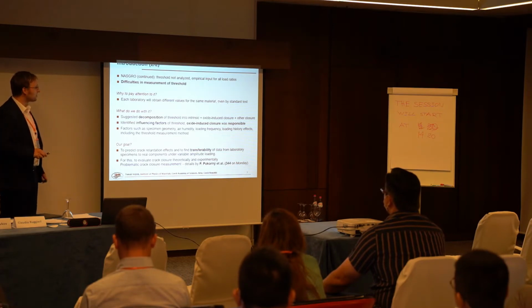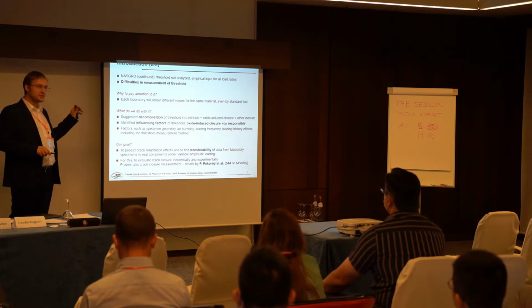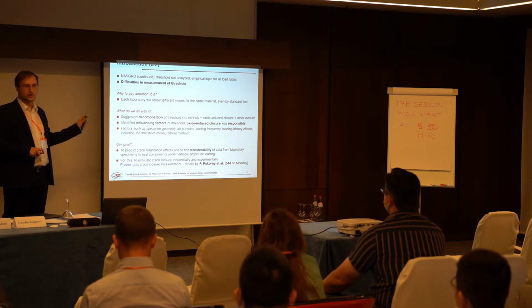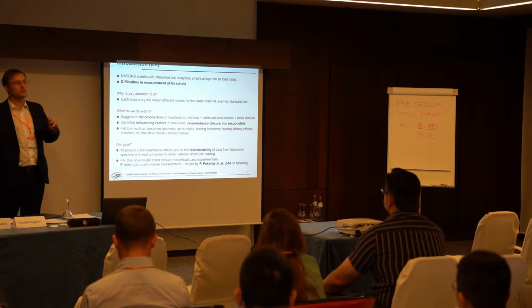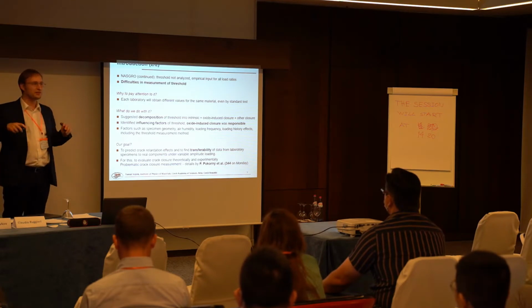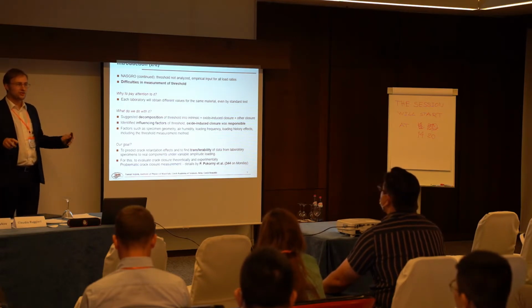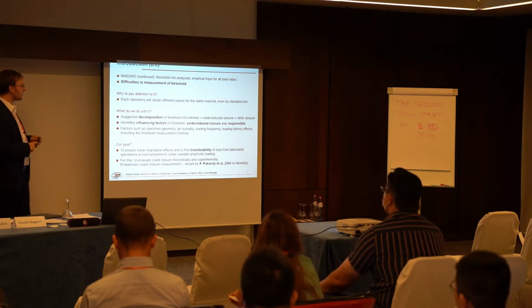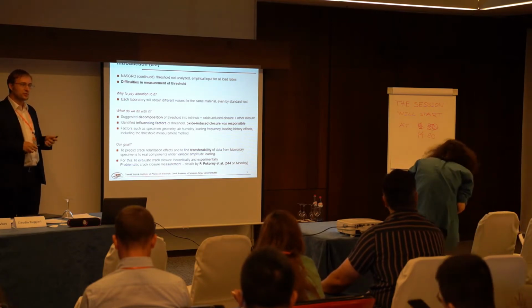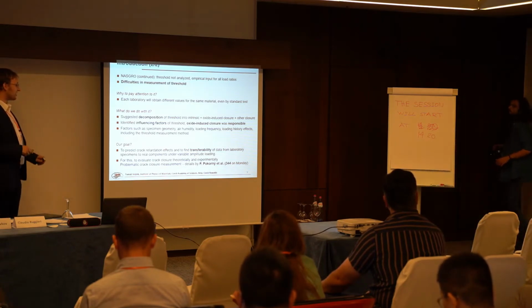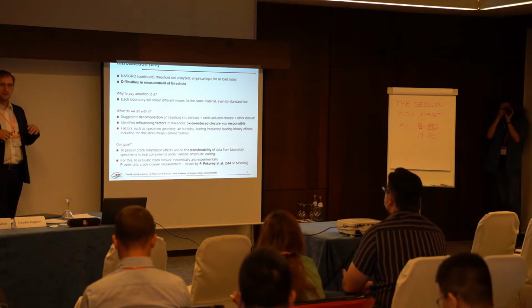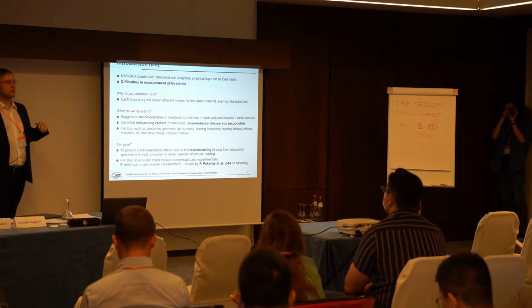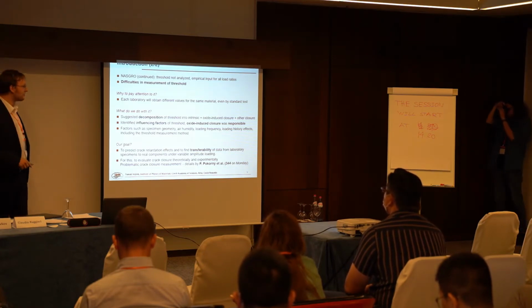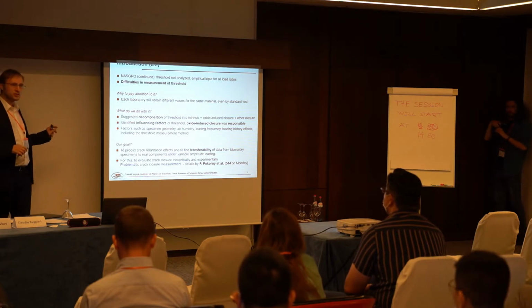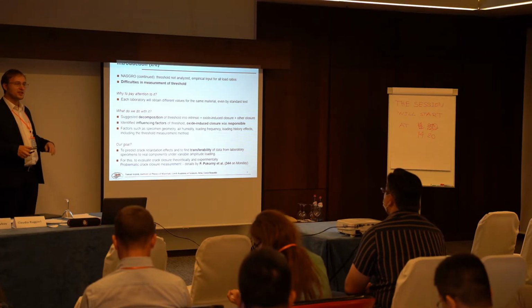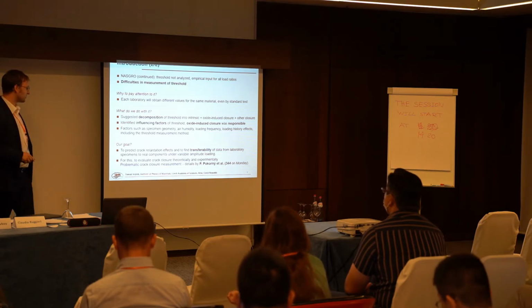And if we talk about, especially in steels, if we measure the threshold value using different specimens, or even using the same specimen but in different laboratories, we can reach different values. And actually we found that oxide-induced crack closure is responsible for all this variation. So in our case, threshold is very important, and we want to know what are the influencing factors on this value. So we divide the threshold to the intrinsic part, to oxide-induced crack closure, and to other closure components.